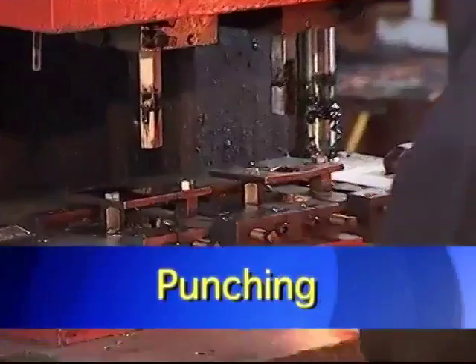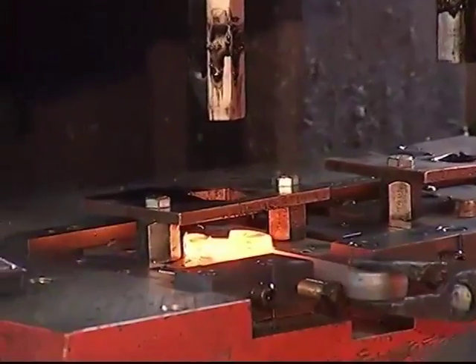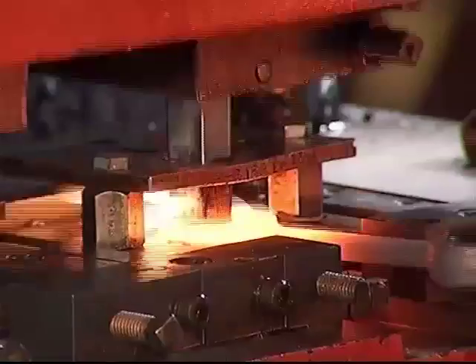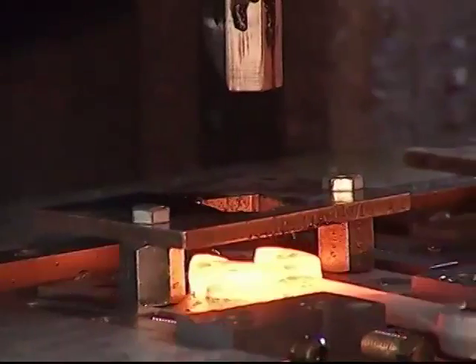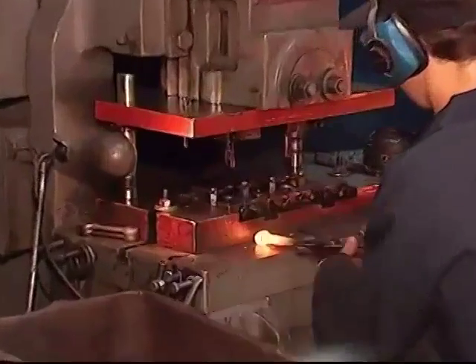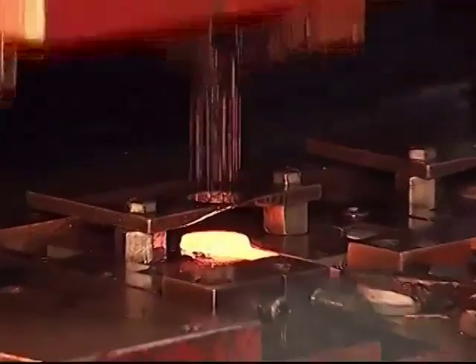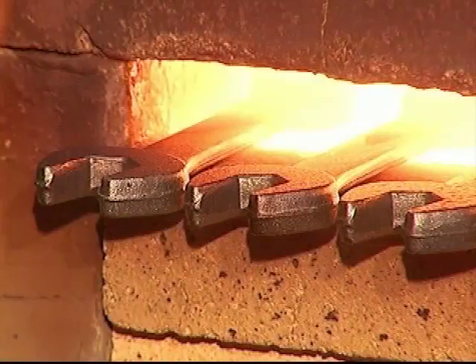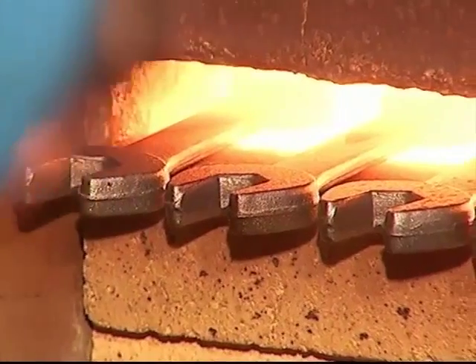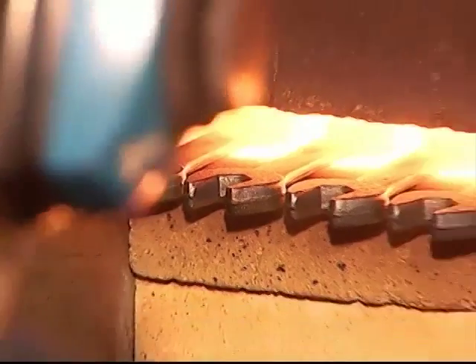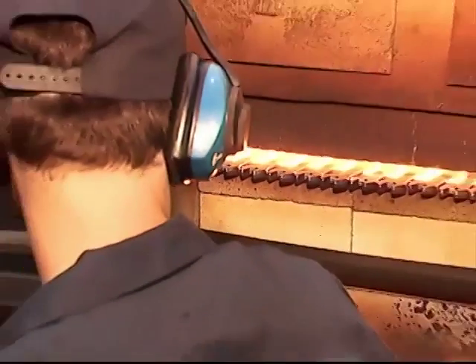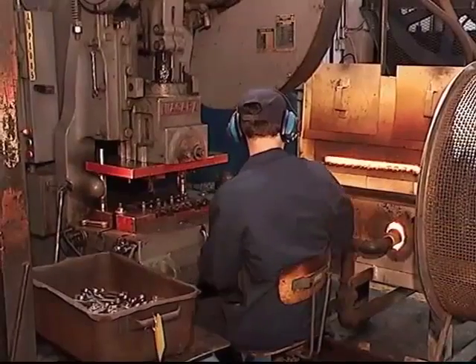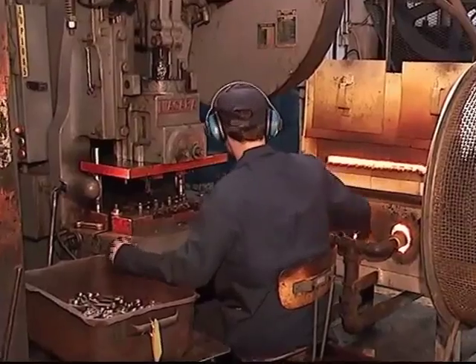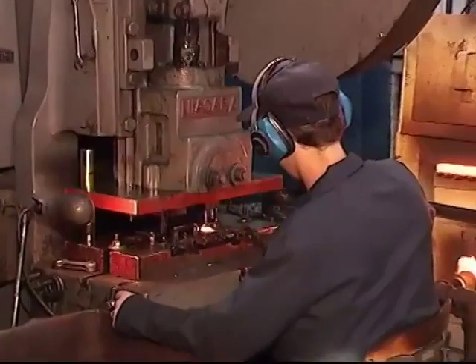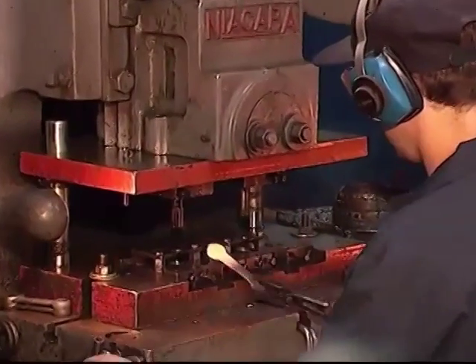Punching. Each end of the wrench is punched. The open end of the wrench is then placed in the press facing right, then flipped over facing left. The boxed end is also punched in 2 steps. Wrench forgings are placed on the furnace shelf, heated by induction to a precisely controlled 1500 degrees, or a cherry red color. Note, the operator does not let the part get too hot. Punching a part that's too hot can lead to scaling and quality issues.